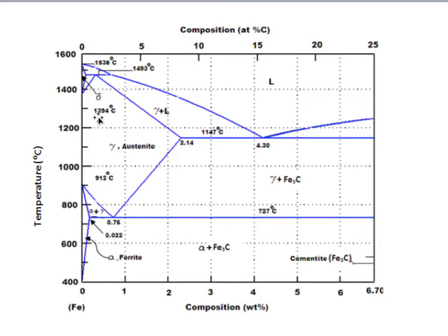And what we see first, when we look at the austenite area, the one-phase austenite, is that when carbon increases, the temperature in which austenite is stable is increasing. It means that austenite exists in a longer temperature interval at higher carbon content, and we say that carbon is stabilizing the austenite phase. Austenite can put carbon atoms in the crystallographic matrix in an efficient way.